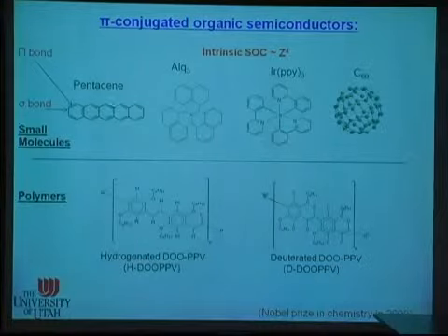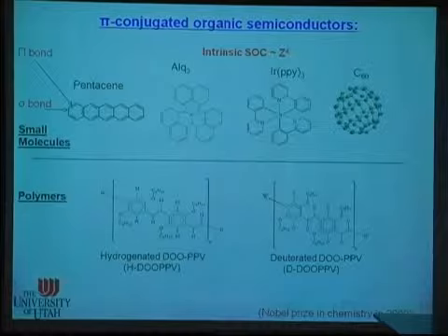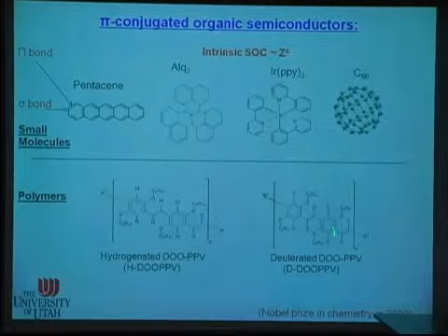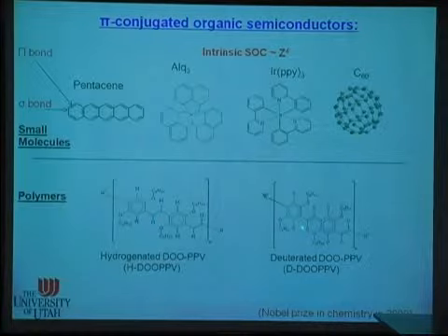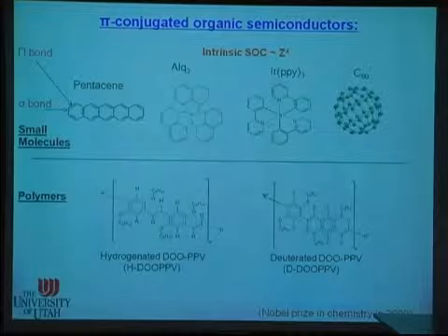Here we have a very small one because the number of protons in carbon is 6, which is small. Or you can engineer even the hyperfine interaction here. If you replace the hydrogen by deuterium, you actually change the hyperfine interaction inside the organic materials.